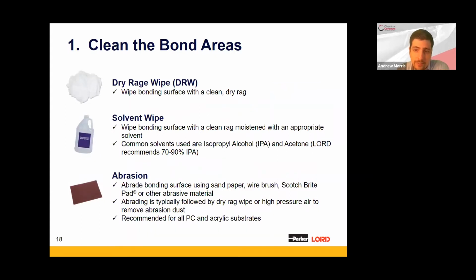Lord acrylic adhesives have the advantage of requiring very minimal surface prep in order to get a good bond. The recommended cleaning procedure is to use a clean, dry rag just to wipe the surface, followed by a surface wipe. We recommend IPA or isopropyl alcohol. Acetone can be used as well. Then a light sanding with a non-woven abrasive product like 3M Scotch-Brite or similar. There's similar constructed abrasives on the market that act the same way. And then a final step is to remove the sanding dust, which can be a dry rag wipe, an additional dry rag wipe, or you can blow off the surface with compressed air as well.